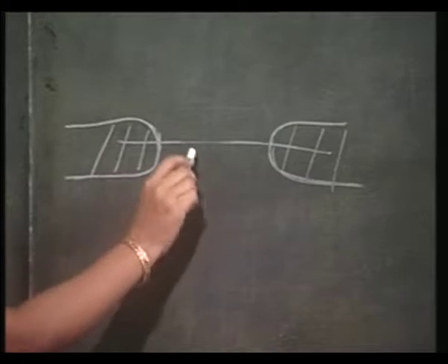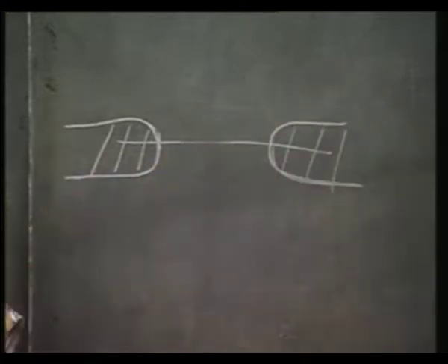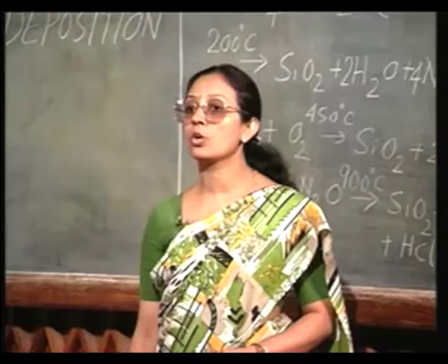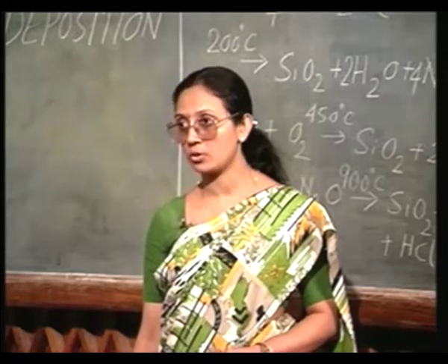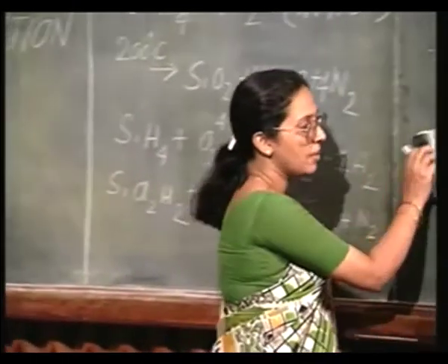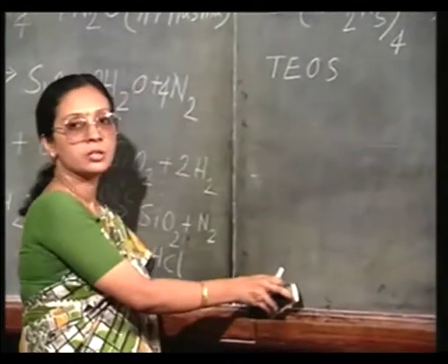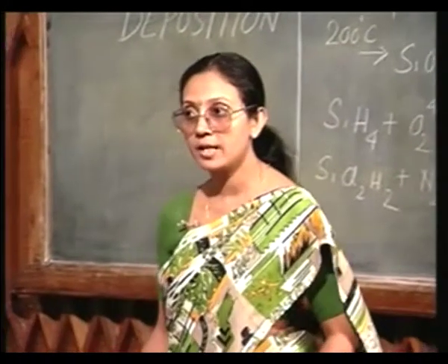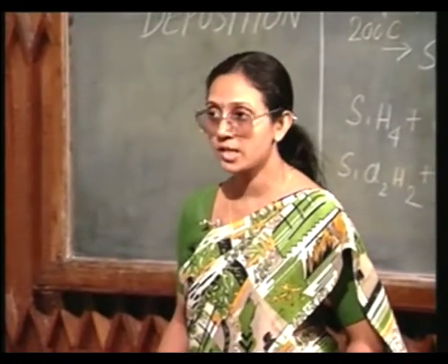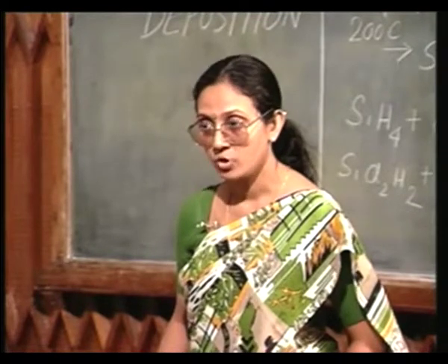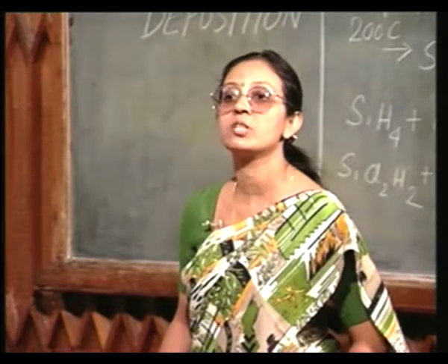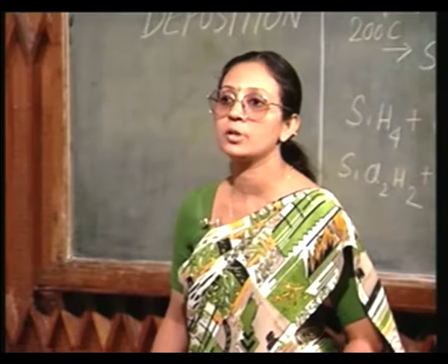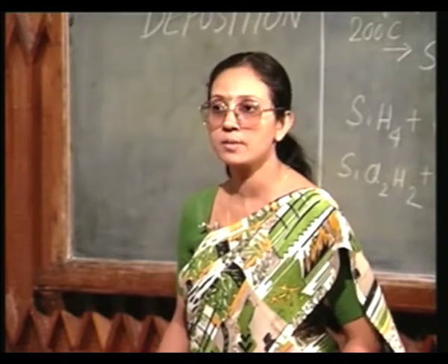The two devices, one transistor here, the other transistor on the other side, can be made isolated by the intervening oxide layer. This is the famous LOCOS (local oxidation of silicon) technology or local oxidation technology, which we will discuss later on. But this is one important feature of silicon nitride, that it is 100 times resistant to oxidation compared to silicon. So, if you do not want some region of silicon to get oxidized, you will have to protect it by a silicon nitride mask.